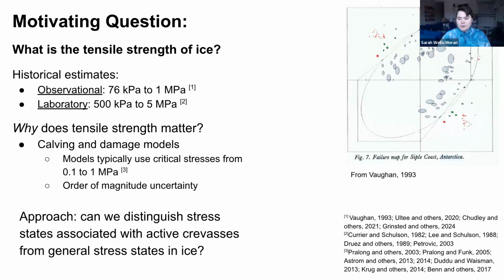So for our approach, we wanted to see if we could distinguish stress states associated with active crevasses from general stress states in ice. And this paper largely follows the methodology of David Vaughan's 1993 paper. You can see a figure from that paper on the right. David Vaughan did this entirely with field measurements, and we leveraged having satellites now and vastly more data points, so we can constrain this range a lot further.